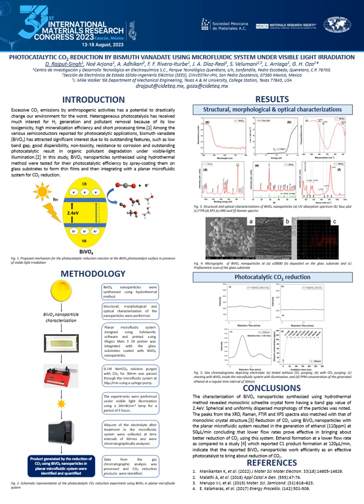Final conclusions: the nanoparticles were synthesized using the hydrothermal method. After characterizations, we confirmed that they were indeed monoclinic scheelite form, and we were interested in monoclinic scheelite form because multiple reports have mentioned that it is the efficient form to bring about carbon dioxide reduction as compared to the tetragonal zircon form or tetragonal scheelite form.